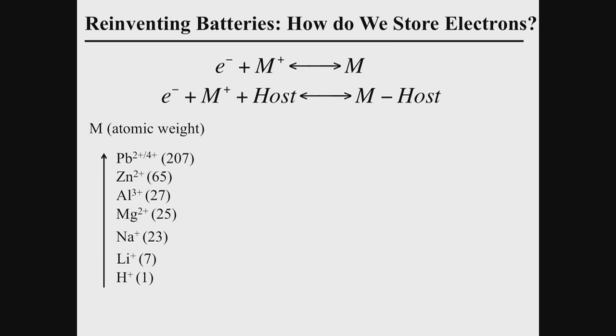Now you want to pick this M, that's the ions. You want the lightest weight, and in the periodic table that is hydrogen, the proton. Atomic weight 1, lithium is 7, sodium 23, magnesium 25. But remember, magnesium and aluminum have 2 plus and 3 plus charge. If you put one ion in, it can balance 2 electrons, 3 electrons. So it's good, but there are other considerations. These are some of the elements you see: in a lead acid battery, we use lead and also protons to balance the charge.